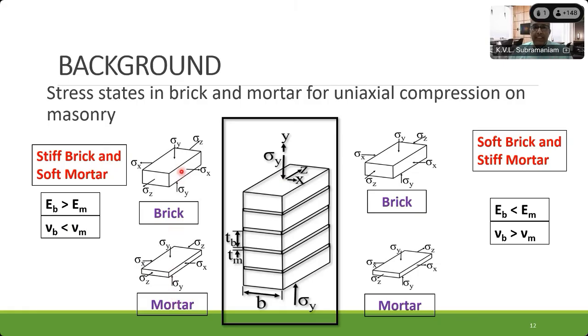Now, when you basically force them to move together at this interface, what happens? You develop a triaxial state of stress where the brick goes into biaxial tension. It's being pulled apart in two directions, and a uniaxial compression in the vertical direction. The mortar is actually in a state of triaxial compression. Why? Because the mortar wants to expand more, and its expansion is being checked by the brick, which is stiffer and has a smaller Poisson's ratio. So the mortar is nicely sitting in a triaxial compressive state of stress.